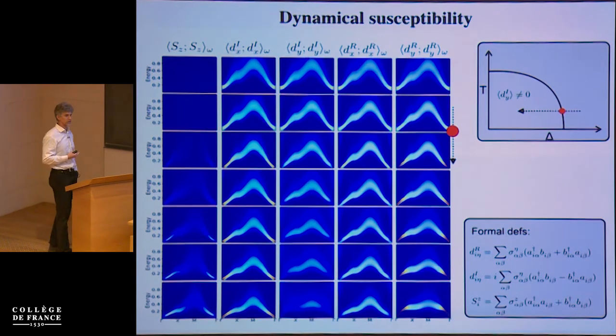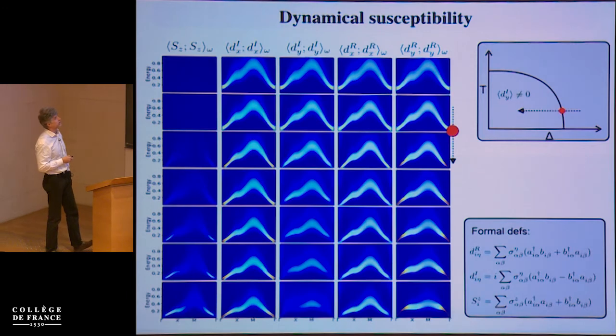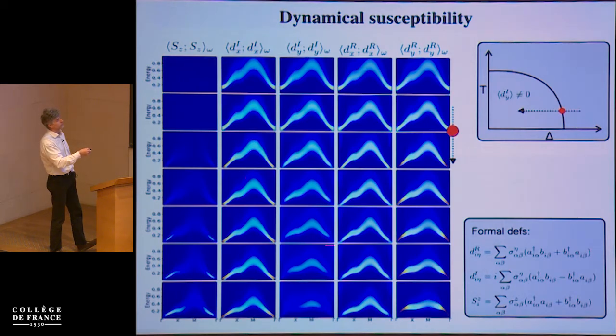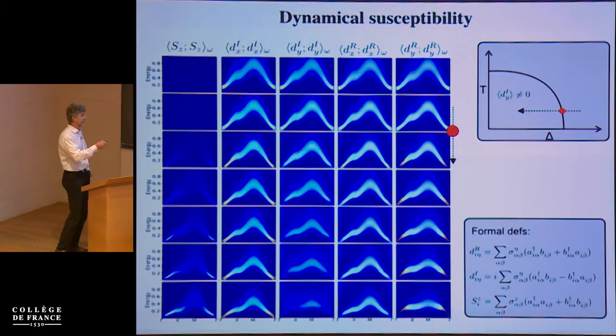This would be essentially the picture I showed you in that simulation in the bosonic picture. These upper two rows correspond to the normal phase, so you can see a dispersion of an exciton with some finite gap. Then we reduce the crystal field, the excitonic gap closes, and when we get to the ordered phase, we get...